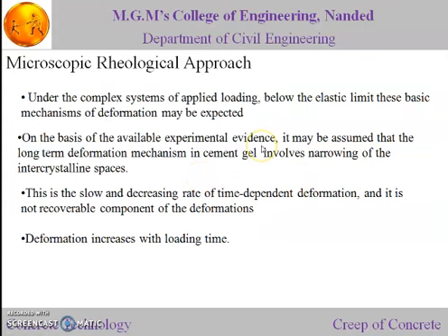On the basis of available experimental evidence, it may be assumed that the long-term deformation mechanism in the cement gel involves narrowing of the intercrystalline space. This is a slow and decreasing rate of time-dependent deformation, and it is a non-recoverable component of the deformation. Deformation increases with the loading time. So this microscopic rheological approach gives us an idea of how creep takes place inside the concrete.